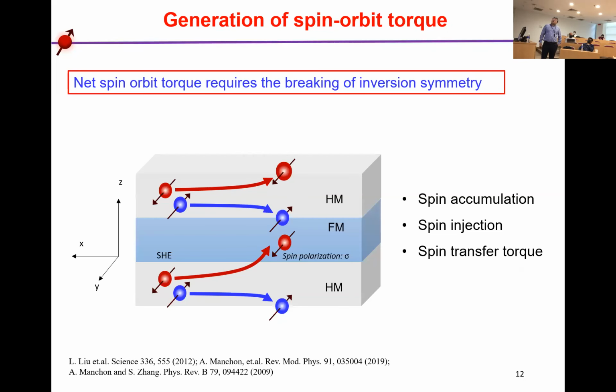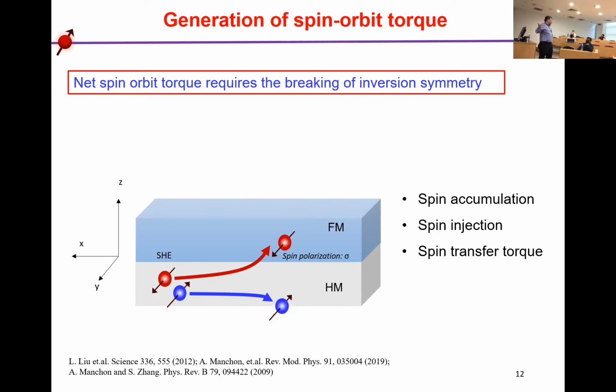And in order to generate a net spin-orbit torque, we need to break the inversion symmetry. For example, here, with this ferromagnetic layer, if on top and bottom there are the same heavy metals, we suppose the interfaces are the same. Therefore, you can see the torque exerted on the ferromagnetic layer will cancel each other. So this has inversion symmetry. But if we remove the top layer, now in the bilayer structure the top interface and bottom interface are different. This will cause inversion asymmetry, so we can generate a net spin-orbit torque on this ferromagnetic layer.